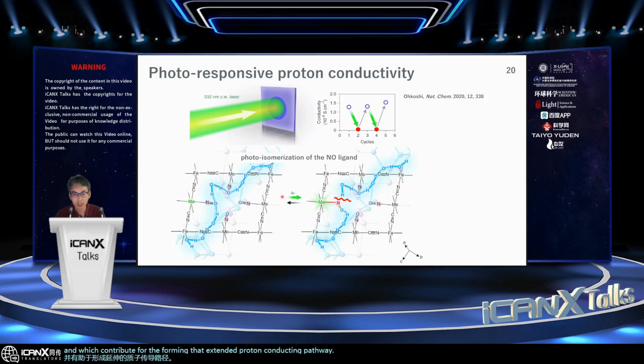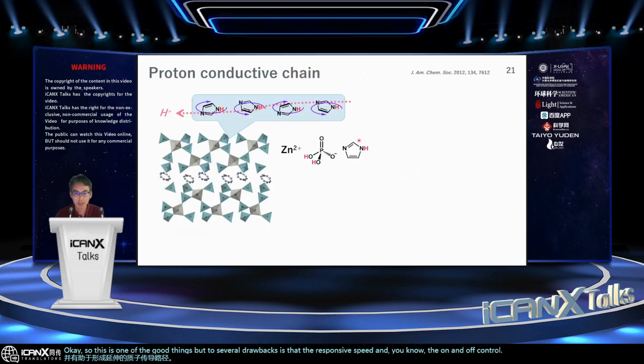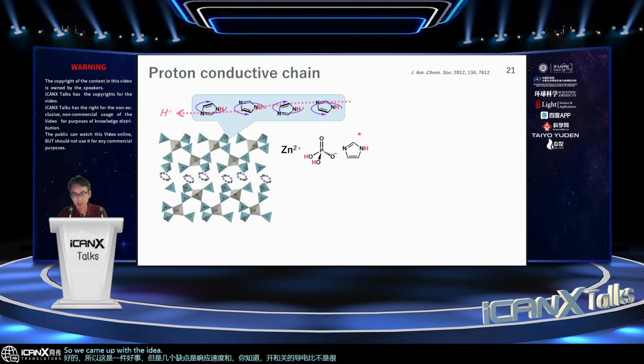So this is one of the good things, but several drawbacks are that the response speed and the on and off conductivity ratio were not very high. So we came up with the idea of how this metal organic framework-based glass can contribute to controlling the proton conductive behavior by photoirradiation. This is another simple example made by zinc, phosphates and imidazole.